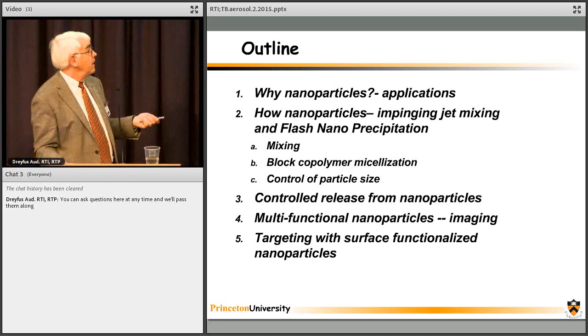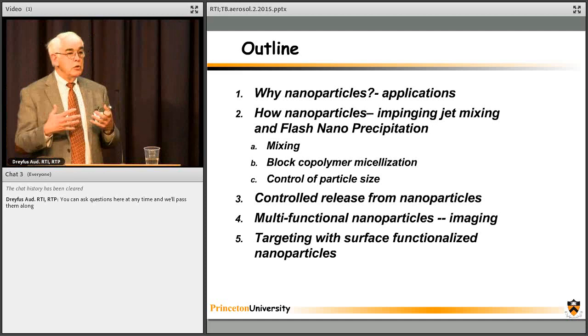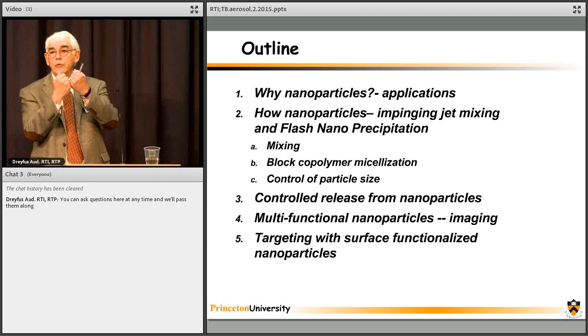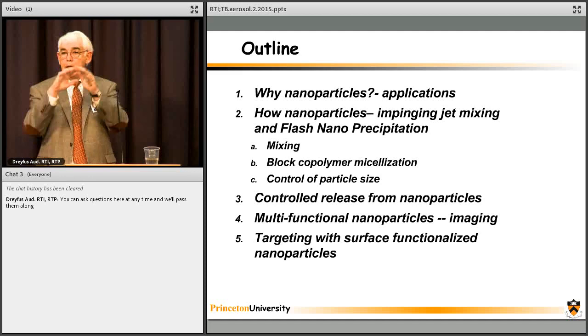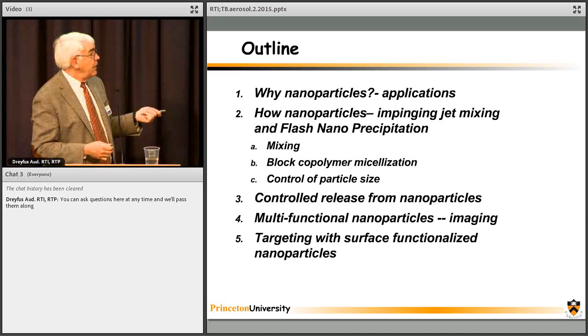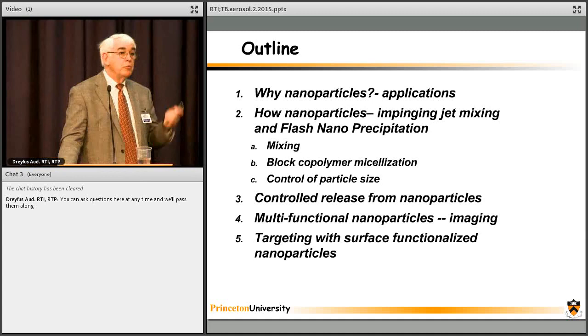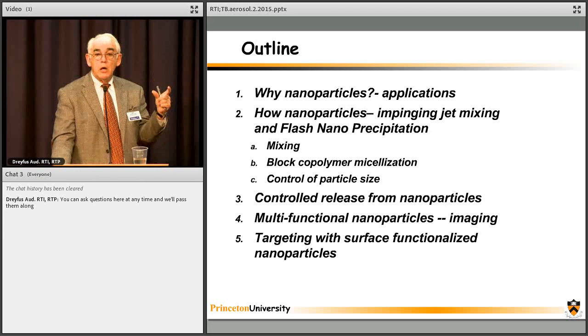And then multifunctional nanoparticles: in this rapid precipitation, as long as the components are hydrophobic, they don't care what they are, they're going to stick to the first thing they see because they're so supersaturated. So that can be drug A, drug B, or drug A, imaging agent B, any combination. We can make stoichiometric ratios of materials in nanoparticle form. And then targeting and surface functionalization: our technique allows for smaller molecule targeting agents up to 14,000 molecular weight. We can put them on the block copolymer and quantitatively assemble them.